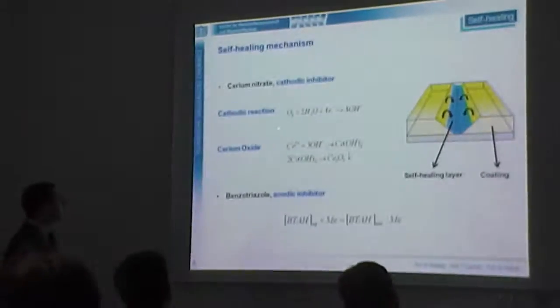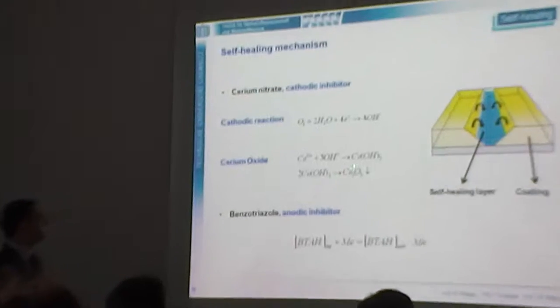In the case of cerium nitrate, corrosive solution penetrates the defect, corrosion inhibitors leach out, and the cerium ions in the defect area can react with hydroxide ions generated by the cathodic corrosion reaction to form cerium oxide. Cerium oxide has a low solubility in aqueous media, which means it will precipitate in the defect to form a layer. Also, benzotriazole leaches out of the film to the defect area and adsorbs on the metal, aluminum or magnesium substrate, in the defect in order to improve the barrier property of the self-healing layer.